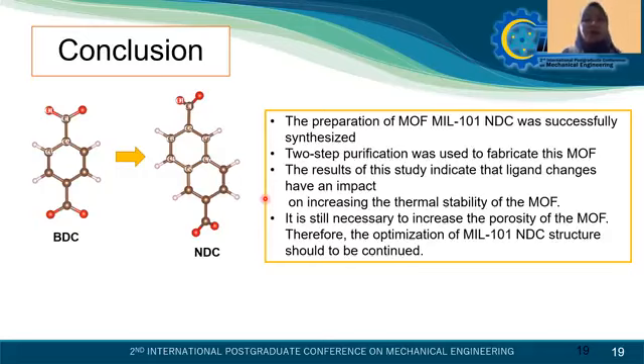But it still needs to increase the porosity of the MOF because the pore volume and also the surface area are still less than the parent. So the optimization should be continued.